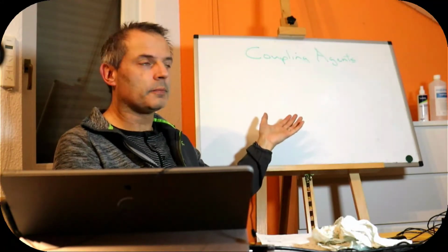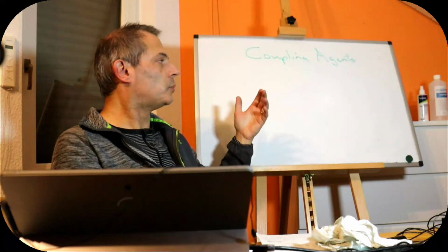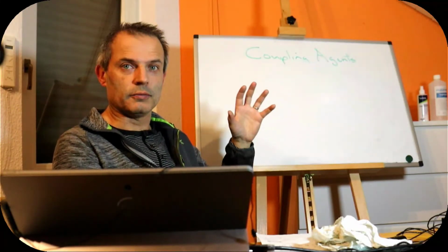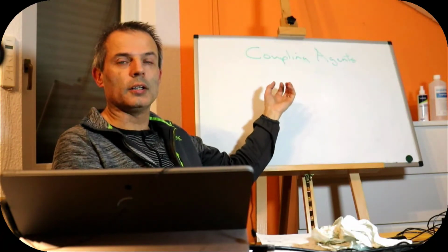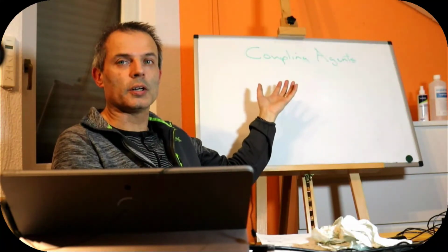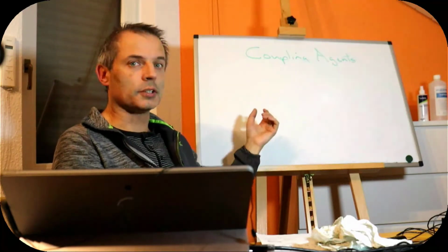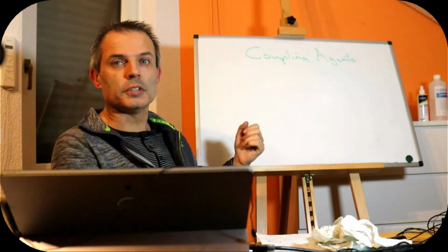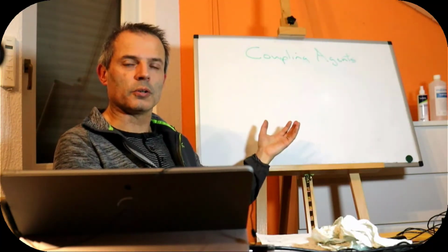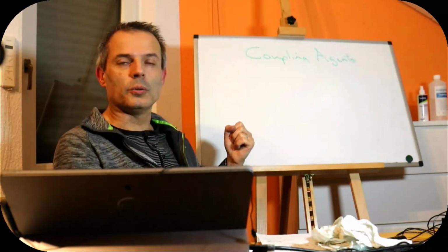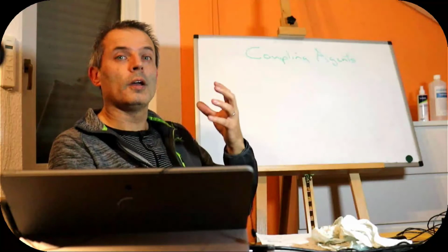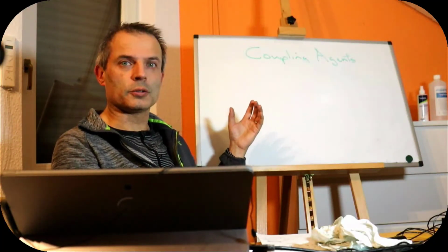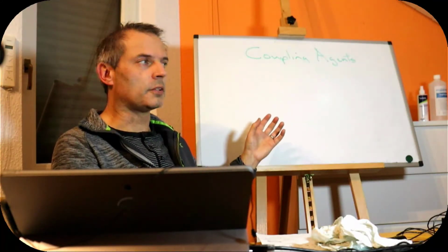As I mentioned, the choice of whether we want to use a silyl chloride or a silyl ether depends on whether we want to react it very strongly now, and it also depends on whether we can deal with the hydrochloric acid that is produced. So it's obviously not very good on surfaces that will be etched by the hydrochloric acid, and also we want to know how long it will last. And also we're interested in how well we can control the thickness of the coating.